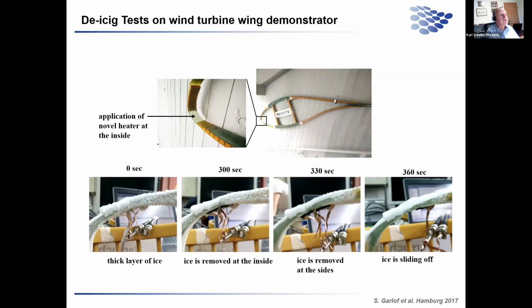That can be used, for instance, for a de-icing test on a wind turbine blade demonstrator. We've patched the heating system to the inside, meaning the epoxy with the aerographite inside, and you can see it heats up and the ice falls down and can be removed. Similar results have also been achieved with carbon nanotubes used for the heating system.